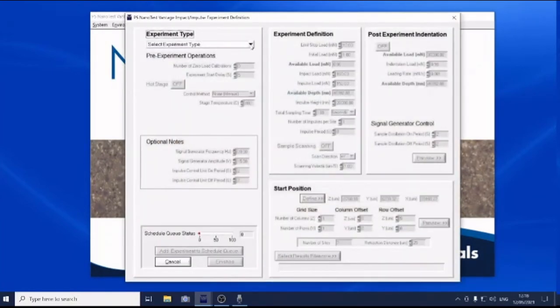So let's go to our first menu here. We select the experiment type. There are a variety of different tests that come under the name impact. The one we're actually doing today is called multiple impulse. A multiple impulse test involves repetitively accelerating a test probe at a sample surface, and then pulling it away again. So we're going tap, tap, tap, tap, tap on the sample surface. You can understand why in the past we've referred to this as a woodpecker test. And we're continuously monitoring the depth of the probe as those repetitive impact events take place.